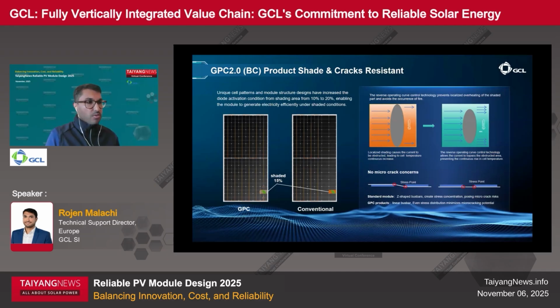Finally, GPC modules minimize microcrack formation and spread. Traditional modules often use Z-shaped busbars, which create stress concentration points. This means cracks can propagate, eventually leading to hotspots and power loss. Our design uses linear busbars with even stress distribution, dramatically reducing crack initiation points and ensuring stable output even if microcracks occur. In short, back contact architecture improves shade tolerance and mechanical resilience, both critical for long-term reliability.